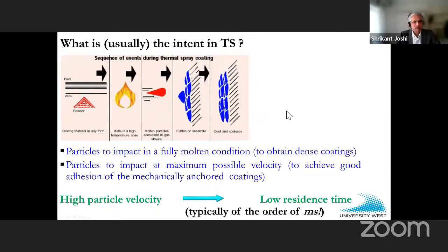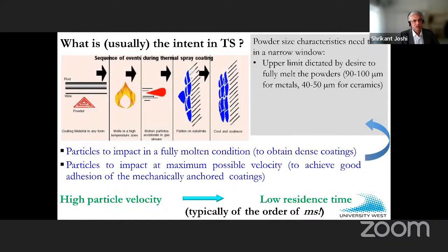And what is usually the intent? The intent is to ensure that the powder particles that you introduce are fully molten to obtain dense coatings, and they also impact the substrate at the maximum possible velocity, because you must remember, these are mechanically anchored coatings, so the adhesion strength is well correlated to the impact velocity. So these are the conditions that I usually highlight trying to meet. And because of this reason of high particle velocity, typically the residence time is of the order of milliseconds. So all the action, melting, acceleration, impact, has to happen in the order of milliseconds.